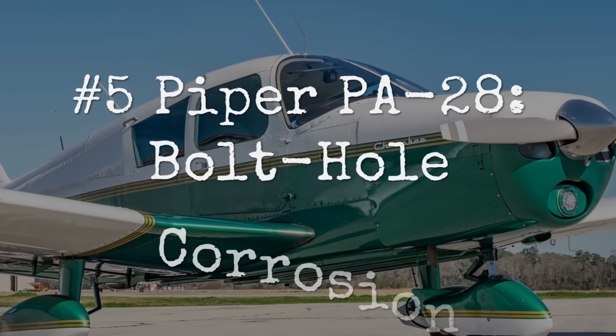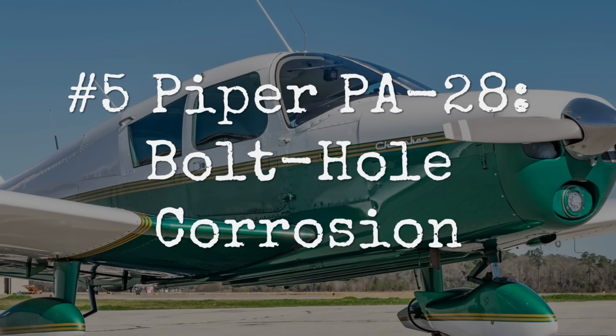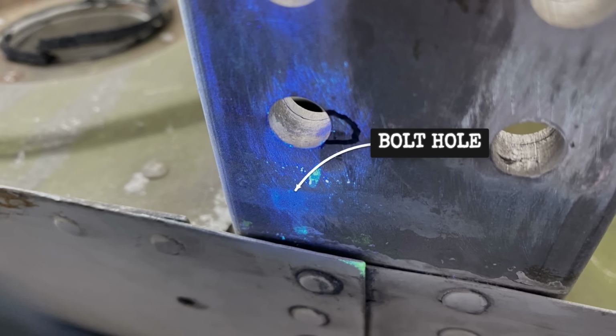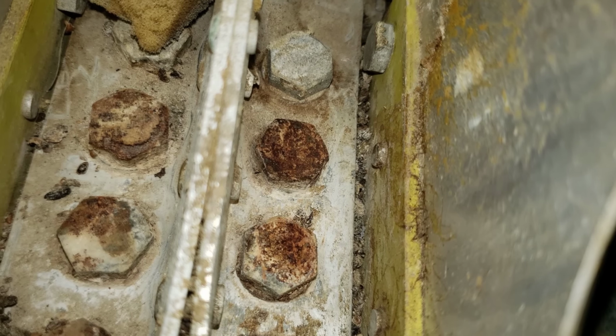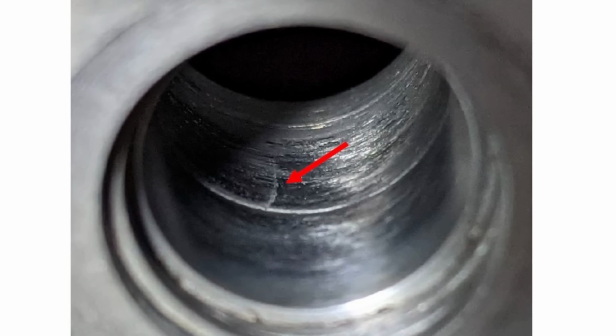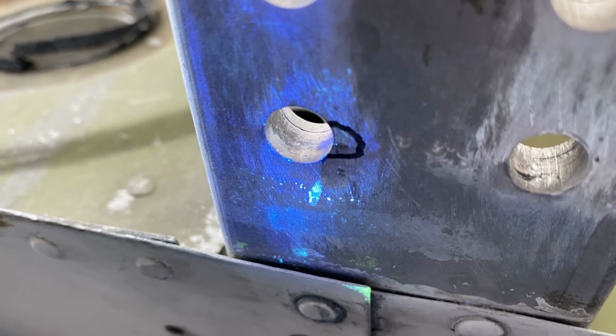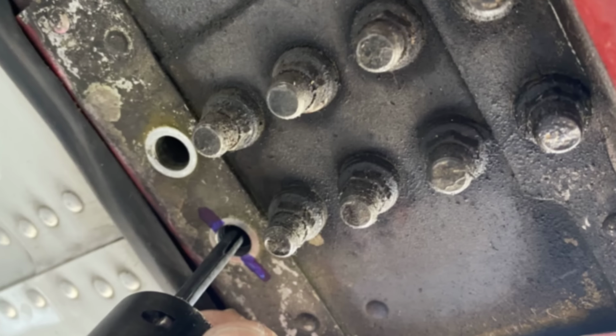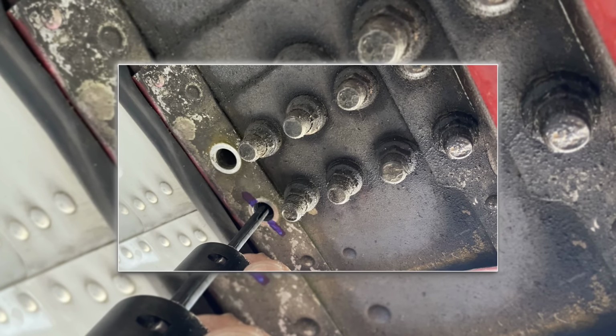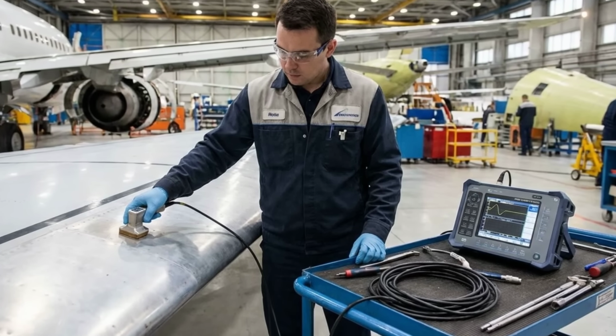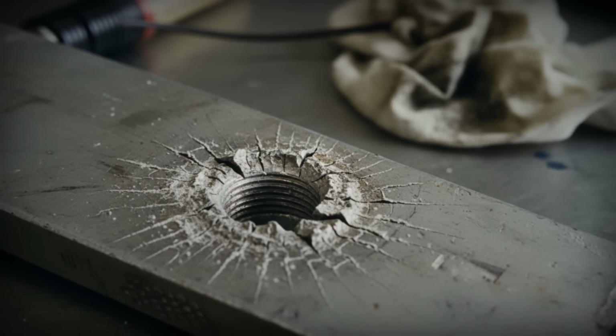A Piper Cherokee or Arrow sits on the ramp, paint gleaming, wing roots tight, and the logbooks look clean. But the real trouble is hiding where you can't see, a few inches of metal around the main wing spar bolt holes. These holes are the only things keeping the wing on the airplane. Over decades, every hard landing and every bump in the air works those holes just a little. The metal stretches microscopically and moisture finds its way in, creating the perfect breeding ground for stress corrosion, cracking deep inside a hole you cannot inspect with a flashlight. Most cracks start so small that even a careful visual check misses them. The FAA's data shows that a standard visual inspection fails to catch the majority of early cracks. By the time you see one, it is already too late.